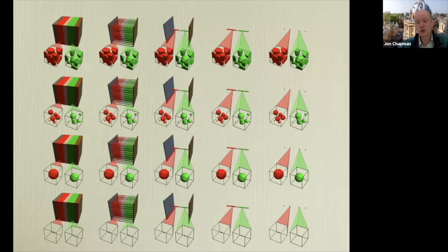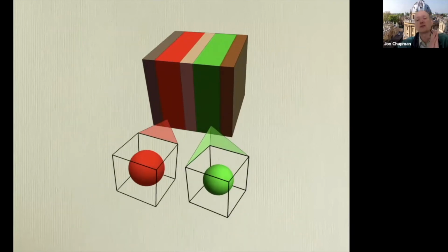distribution is unimodal. You say, well, let me choose a representative size for each particle. And we've been doing some work on that to say, what's the right size to choose? Should you choose the average radius? Should you get the average area right? Should you get the average volume right? Should you choose the volume weighted average of the area? There are all sorts of things you can do, and depending on exactly what you want your model to reproduce, the different choices are appropriate.